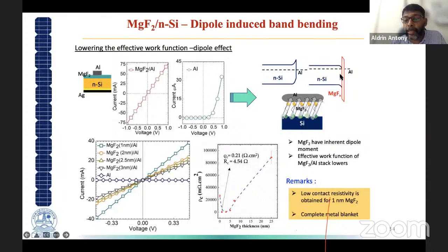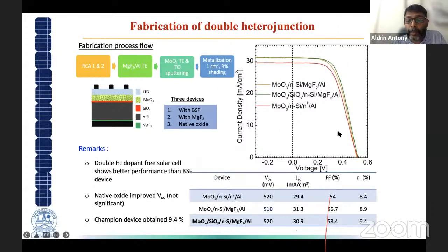When a metal layer, aluminum, and magnesium fluoride come in contact with an N-type silicon, the band bends downwards, giving an opportunity for electron selectivity, and it gives a band offset for the holes to move in this direction. And this has been successfully done to fabricate a device.